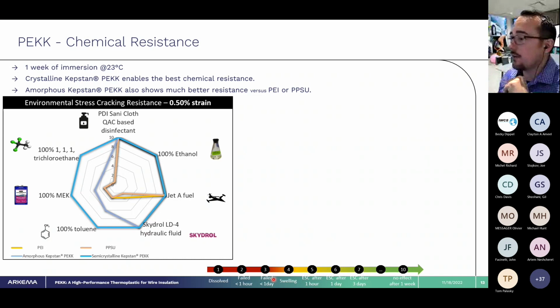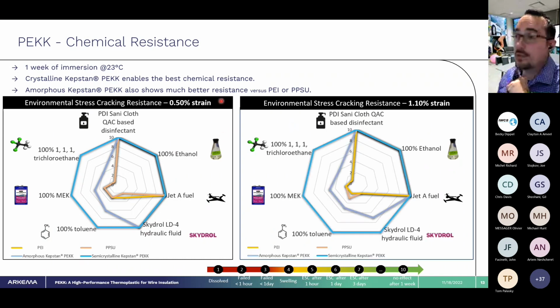I also have it at 1.1% strain. The thing to point out is we are comparing the amorphous PEKK as well, and what you can see is the amorphous PEKK still does better than the PEI and still does better than the PPSU, but it will of course underperform the semicrystalline PEKK. This is a completely expected result, no surprise, but it shows you that depending on your processing and your application, we have the flexibility to have a material that might fit for you.